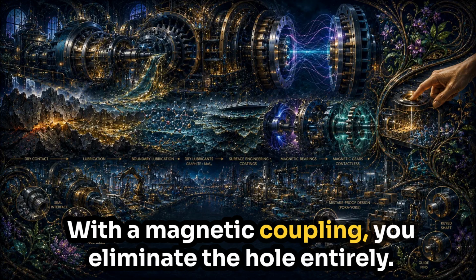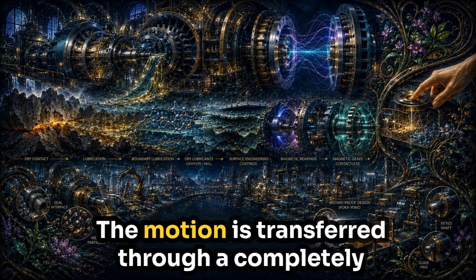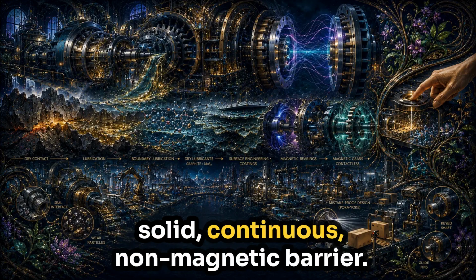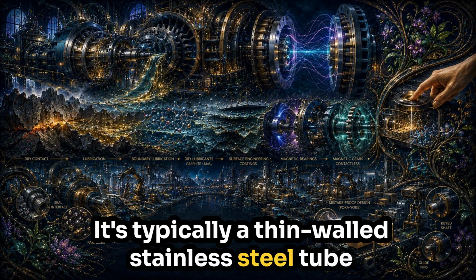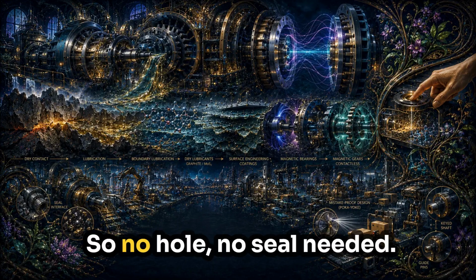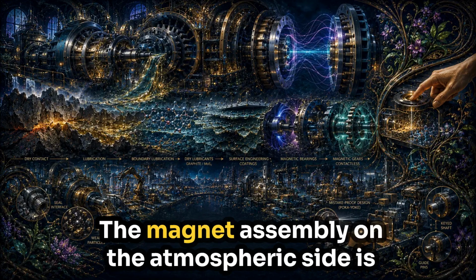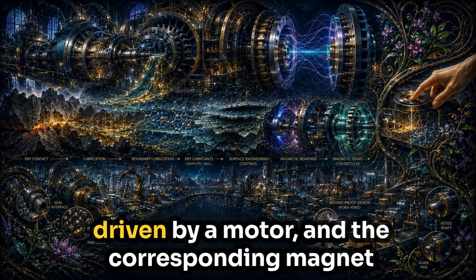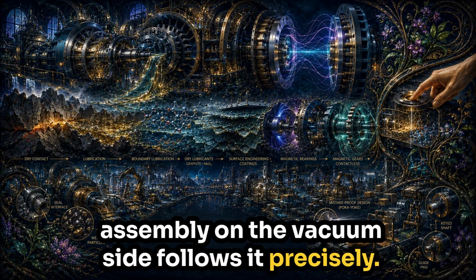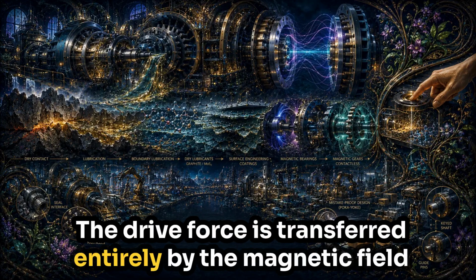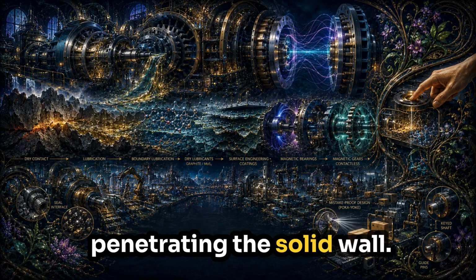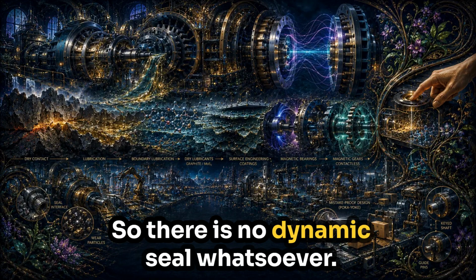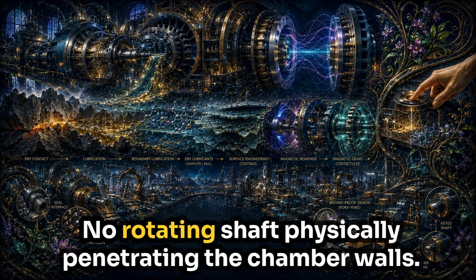With a magnetic coupling, you eliminate the hole entirely. The motion is transferred through a completely solid, continuous, non-magnetic barrier. It's typically a thin-walled stainless steel tube or a ceramic wall. So no hole, no seal needed. Exactly. The magnet assembly on the atmospheric side is driven by a motor, and the corresponding magnet assembly on the vacuum side follows it precisely. The drive force is transferred entirely by the magnetic field penetrating the solid wall. So there's no dynamic seal whatsoever. No rotating shaft physically penetrating the chamber walls.